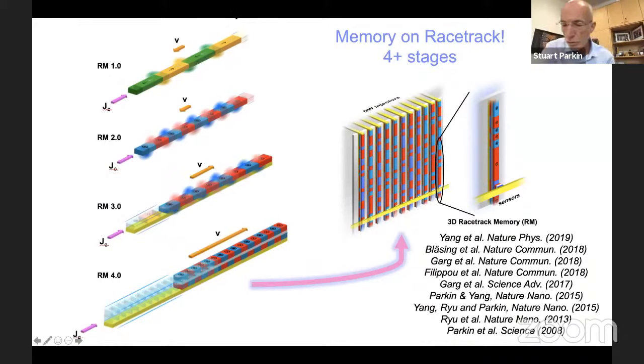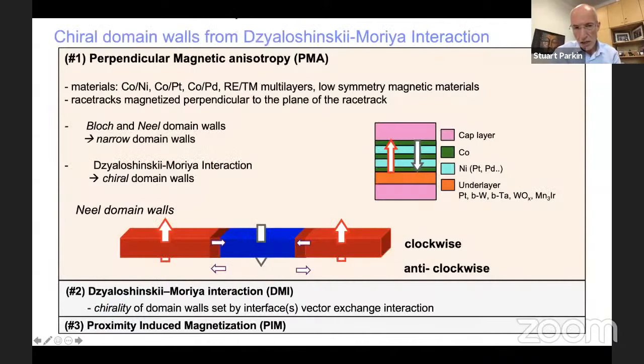So we published quite a few papers over the last few years on Racetrack Memory 3.0 and 4.0. I want to just discuss one or two elements of the technology. In particular, I mentioned already that we create racetracks in which the magnetic moment is perpendicular to the racetrack or the thin film. And we do this by simply creating interfaces. So you take a multilayer of cobalt and nickel. Individually, they're extremely soft magnetic materials, but by creating interfaces on the atomic scale, where the cobalt and nickel layers are just a few angstroms thick, the interfaces break the symmetry and give rise to large perpendicular magnetic anisotropy.